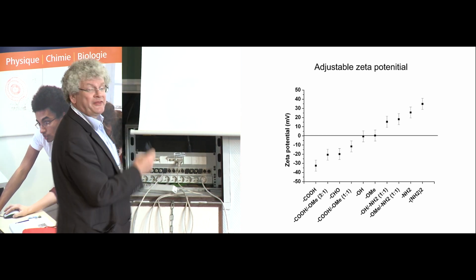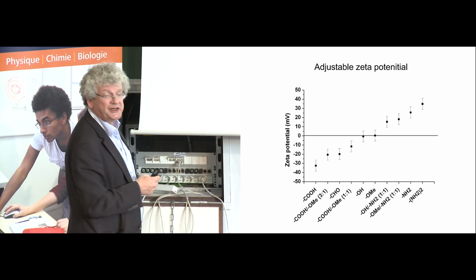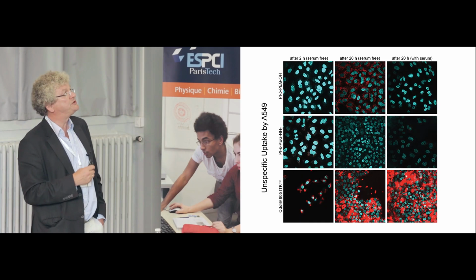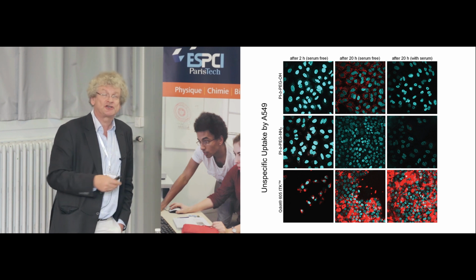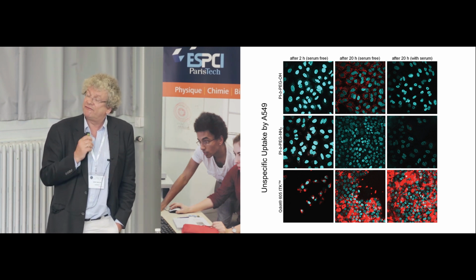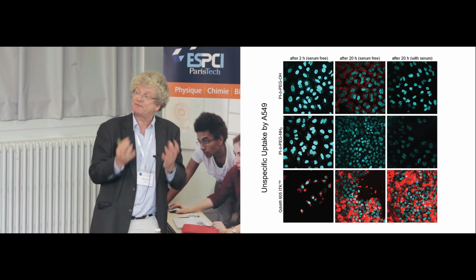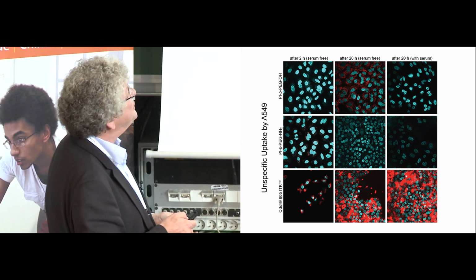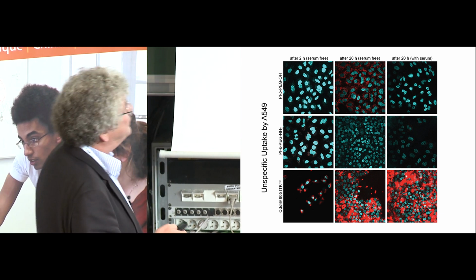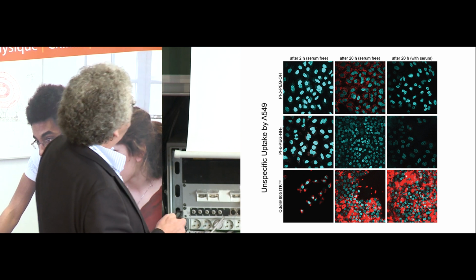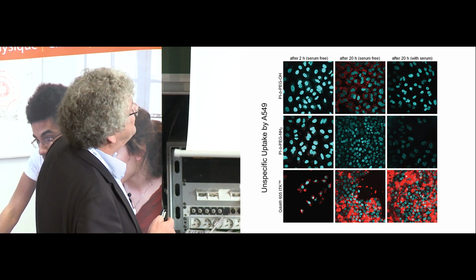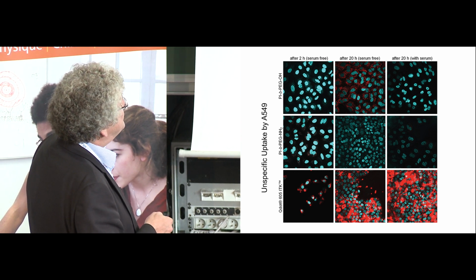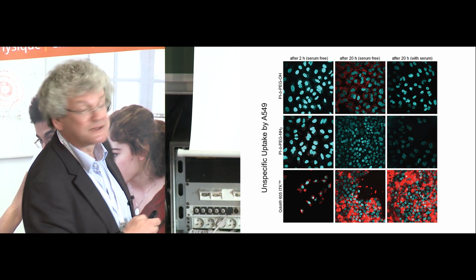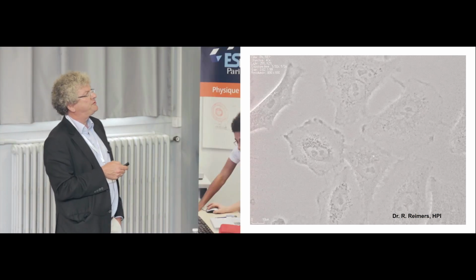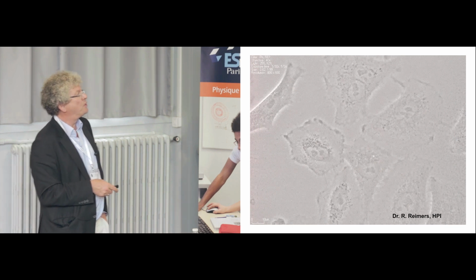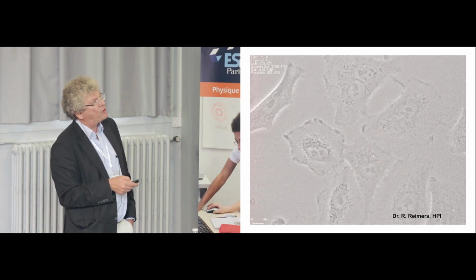We started this something like 7 or 8 years ago, and we ran into serious problems, also rather low circulation times, until a very sophisticated optimization of all this encapsulation process started. And one thing of this optimization was also variation of the polymer block lengths. You can see here uptake studies in cell cultures, and we used diblock copolymers with different molar weights. So here is a rather small one, 4,500. This is 100 monomer units approximately, and then a little bit more here, 8,000.